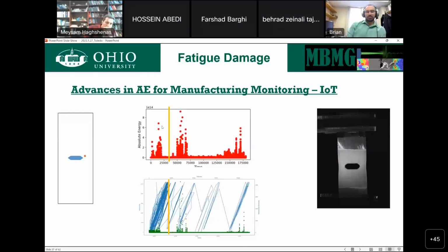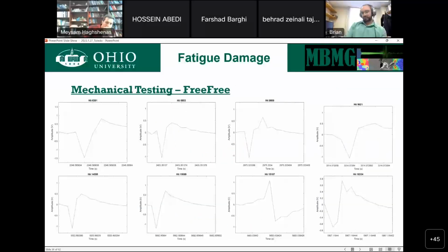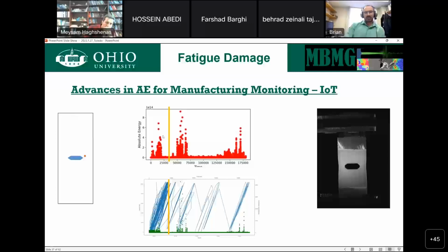So we see a bunch of activity. Each of these red dots represents one of these types of waves. We see a lot of activity early, kind of dies off right around where the crack's nucleating, and then we see more activity right about where it's not just nucleating anymore, but starting to grow, and then it kind of decays again before building up right before final failure.